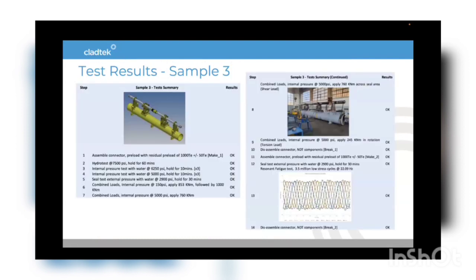So this last specimen was put onto the bending rig, 4-point bending, and subject to combined tension and bending, etc. And this sample also was sent to DNV in Singapore for further high cycle low stress testing.